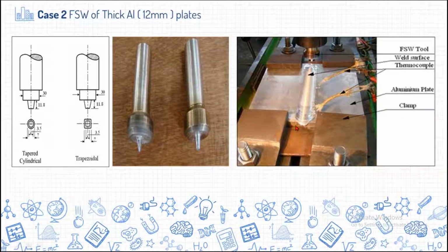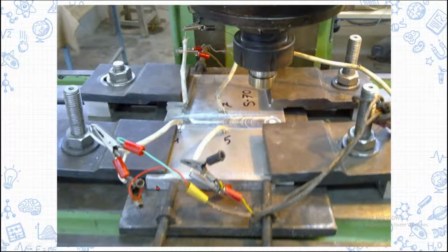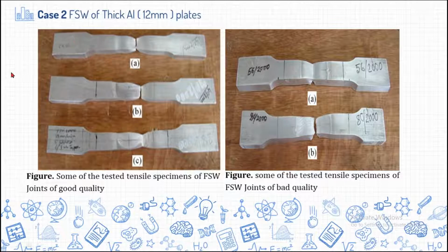So this is the setup of the welding plate. If you see more thick welded plates, we have performed welding over here at IIT Kharagpur, and these are the tensile testing samples. Some good welding obtained. See, the failure takes place just away from the center of the welding over here. So some good quality weld joints, and some bad quality welded joints which failed at the center of the weld zone for these particular parameters, like 56 welding speed and 2000 RPM, and 80 and 2000 RPM. Some bad quality welded joints observed over here.